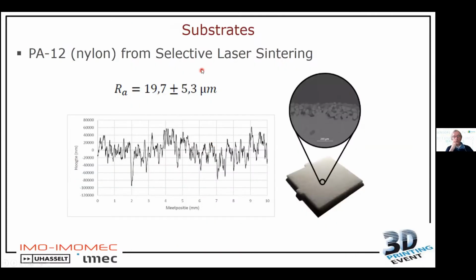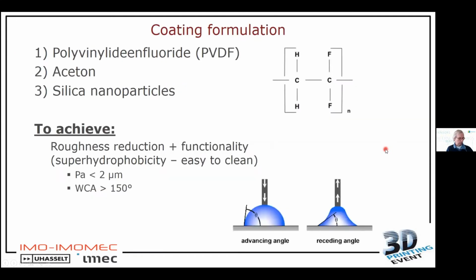Okay, let's focus on the substrates. We use these PA12 substrates made using selective laser sintering. If we measure the roughness just after they are 3D printed, the roughness is around, let's say, 20 micrometer. Here you see the profile, and here you see a cross section of the structure, where on top you see this quite porous substrate. That's why ultrasonic spray coating is so interesting, because what we do now is take PVDF as a polymer, and acetone as our solvent. In the second step, we also will use silica nanoparticles to play with the ink formulation. We do that to achieve roughness reduction, plus adding this functionality, the superhydrophobicity, or easy to clean.